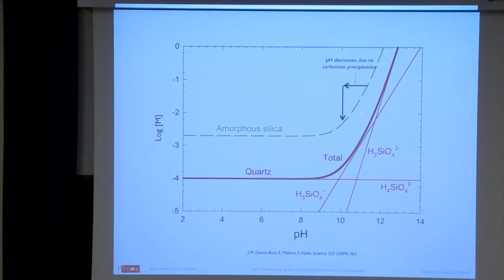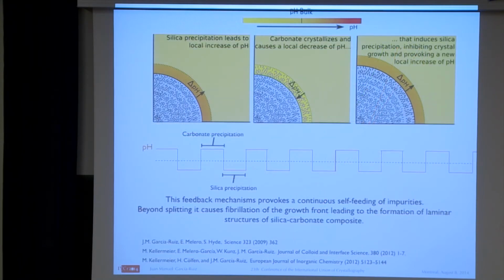But the precipitation of silica, well, increases the pH. And the increase in pH, right, what happens is that it then provokes the precipitation of carbonate again. So this is a self-coupling mechanism, okay, that produces a variation of pH in the growth front, okay? And this is the mechanism that is able to produce this complex morphology, because this is something that you can provide. Many people do